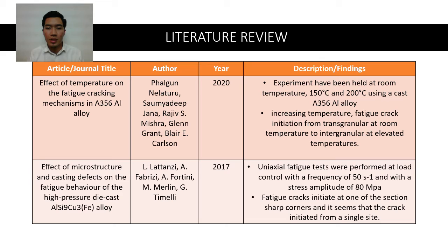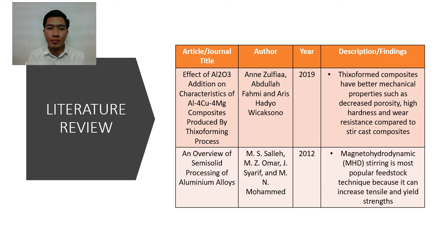By increasing the temperature, fatigue crack initiation changes from transgranular at room temperature to intergranular at elevated temperature. Second is Effect of Microstructure and Casting Defect on the Fatigue Behavior of High Pressure Die Cast alloy. This article was published in 2017, where uniaxial fatigue tests were performed under load control with a frequency of 50 Hz and a stress amplitude of 80 megapascal. The fatigue crack initiated at one of the sharp corners of the section, and it seemed that the crack initiated from a single site.